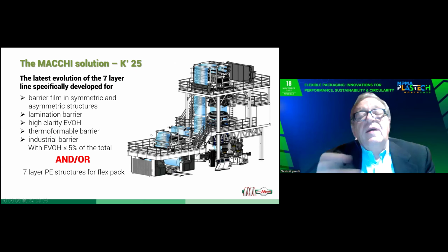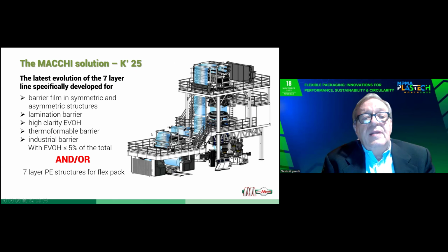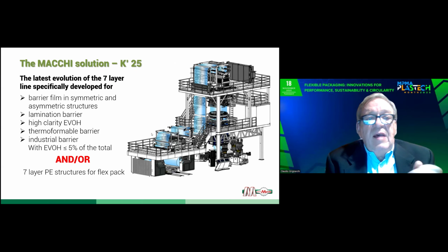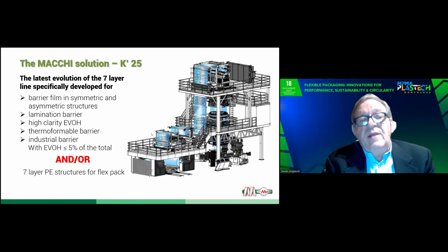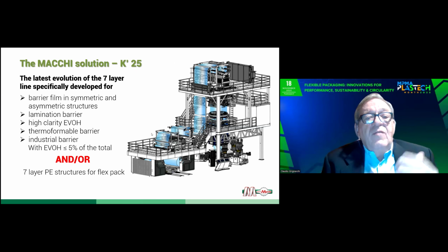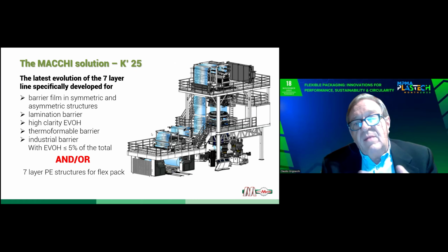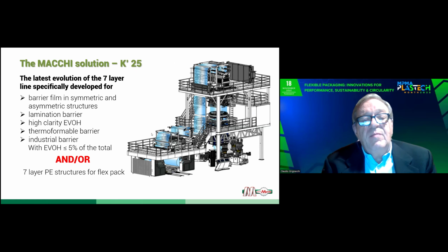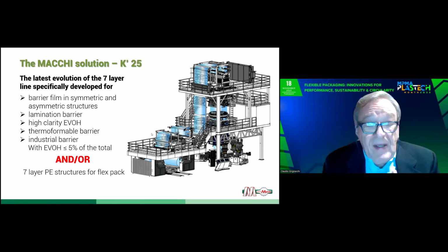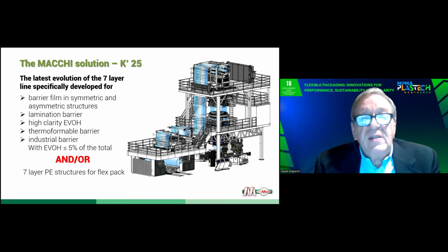During K25, we presented our new 7-layer line developed for barrier film in symmetric or asymmetric structure, for the production of lamination barrier films using high clarity EVOH, with EVOH lower or equal to 5% of the total. At the same time, the line can produce 7-layer polyethylene structures for flexible packaging.